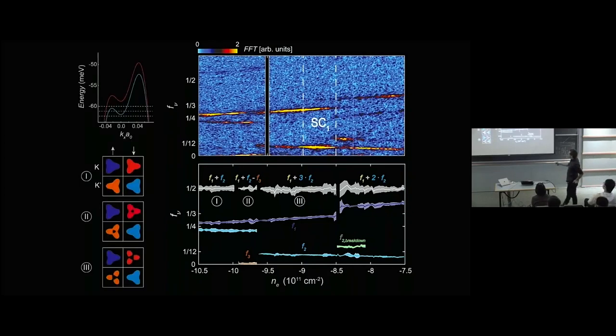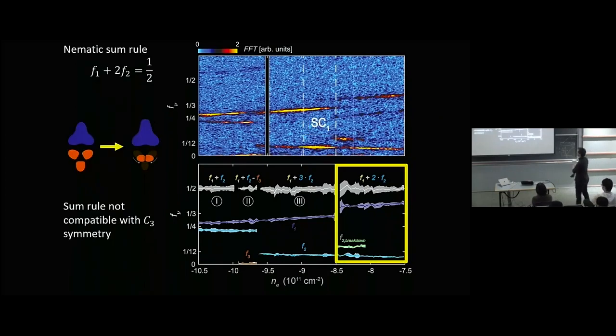So this is what the band structure looks like. You have this splitting in each valley between the different spins. Spin is still basically a good quantum number, but now your Kramers pairs have opposite spin and opposite valley, and there's not the spinless time reversal. So now SC1 looks like it's emerging from the single particle picture, but then a funny thing happens as you keep lowering the density and approaching the Van Hove singularity. The first symmetry that breaks here seems to be rotation symmetry.